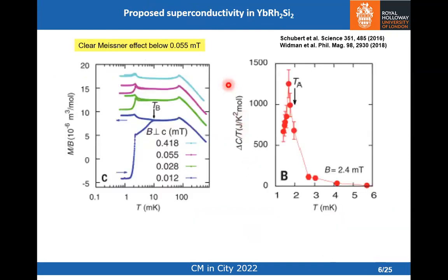So now to superconductivity. This was the 2016 result. So for me, only this is the evidence for superconductivity in this material. From this paper, in very low magnetic fields, here we've got a field of 12 microtesla, there is evidence of strong diamagnetic screening. There is hysteresis in that. And there are also measurements of AC susceptibility, which show diamagnetic screening.